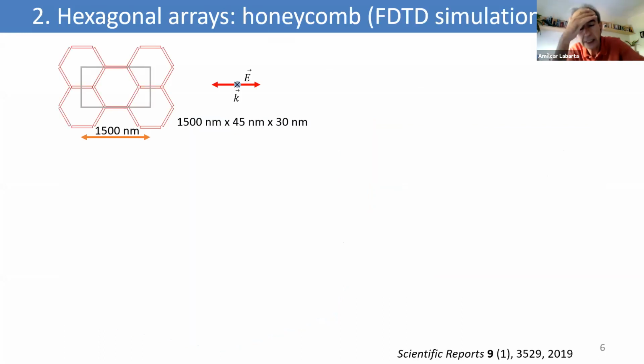Okay, this is my first example, and I am going to use this example to show you how the threefold symmetry hampers the common usual near field excitation of the elements. This is a honeycomb array of bars, but the bars are not touching each other. There is a small gap between them, and this small gap is intended to absorb energy from the incoming radiation in the form of the near-field excitation.